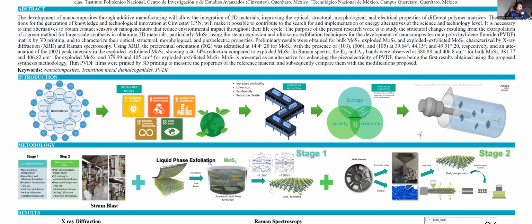In this two-step process, the first step is the steam blast, which is a steam explosion, a rapid expansion process that separates the bulk molybdenum disulfide into different layers. And the second step is to apply ultrasonic exfoliation, which uses high-frequency ultrasound waves to further separate and reduce the molybdenum disulfide into nanosheets. The exfoliated molybdenum disulfide was then washed, dried, and characterized using XRD, X-ray diffraction. We also applied SEM and TEM microscopy, Raman spectroscopy, and UV-Vis spectroscopy. This method enables large-scale production of semiconductor-grade, layered molybdenum disulfide with minimal environmental impact.